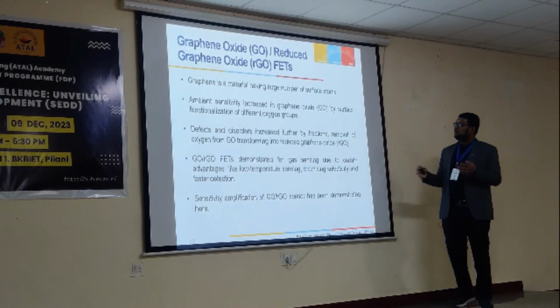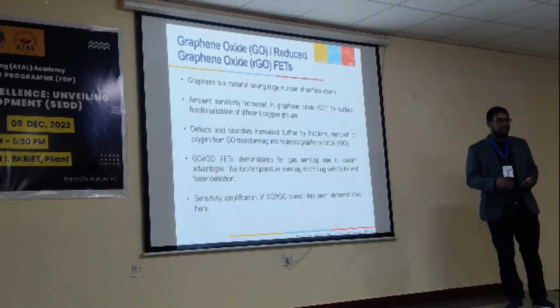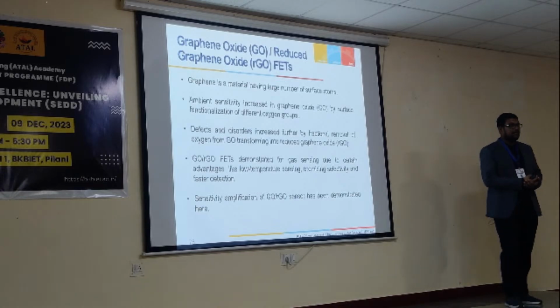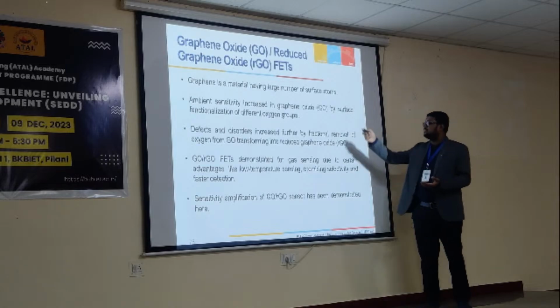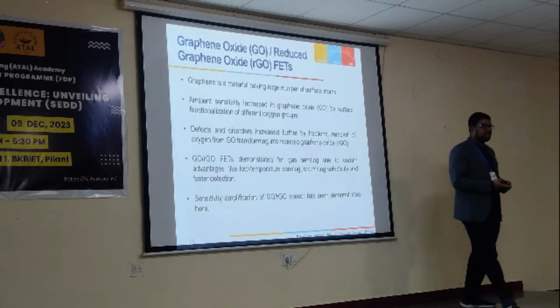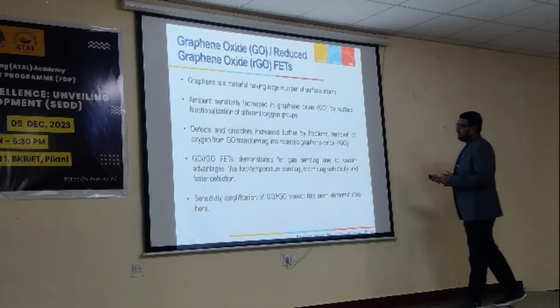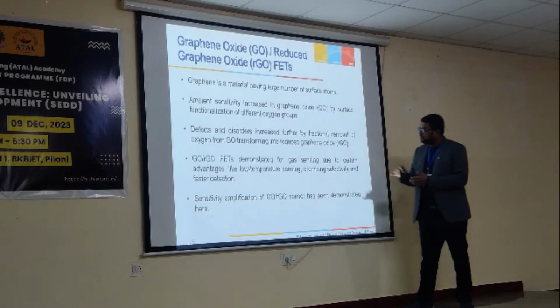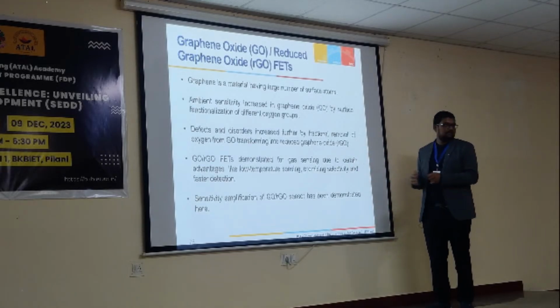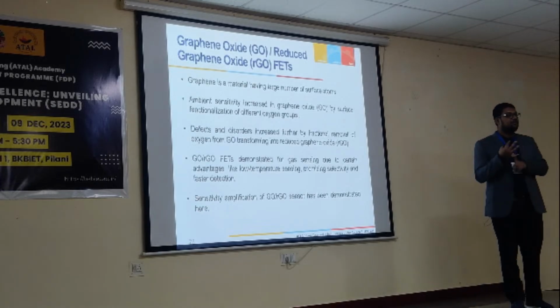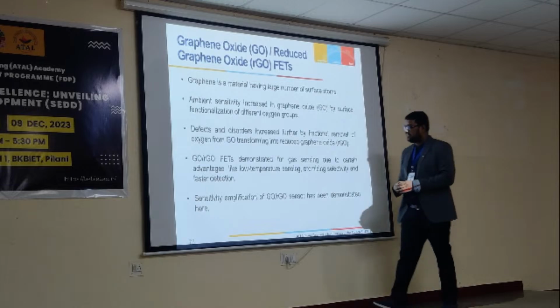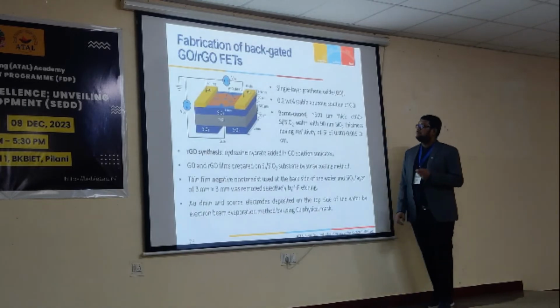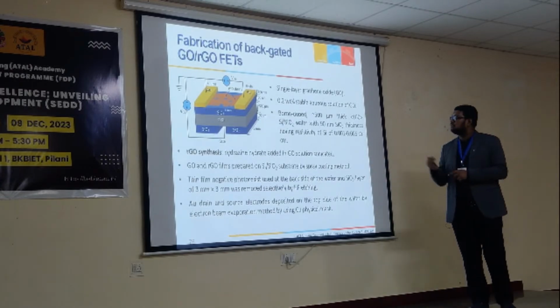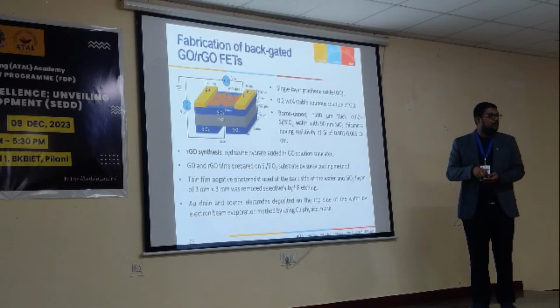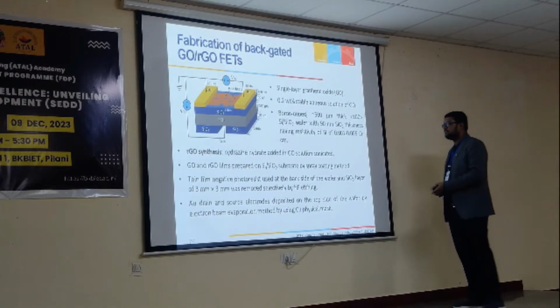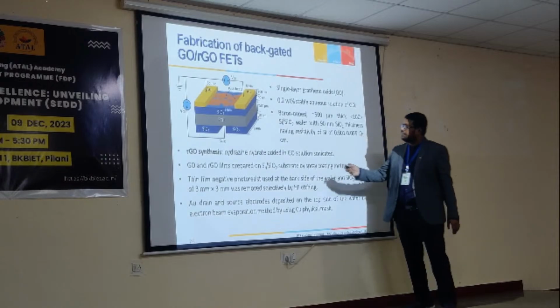Okay, so when we prepare this soluble graphene oxide solution, then we can easily drop cast it over the silicon dioxide substrate. That was the challenge actually, because we have not synthesized this graphene oxide. We purchased it from Sigma Aldrich, a very well reputed company. Then we further reduce this graphene oxide by removing some oxygen functionalized groups from the surface, which is called reduced graphene oxide. So graphene can be represented in forms: graphene oxide and reduced graphene oxide. Ultimately we tested with reduced graphene oxide. The deposition was possible only due to the solubility of graphene oxide in water. Then in a controlled way we drop casted it over the Si/SiO2 substrate, and then we removed some oxygen functionalized groups. So here you can see the structure that we have fabricated.